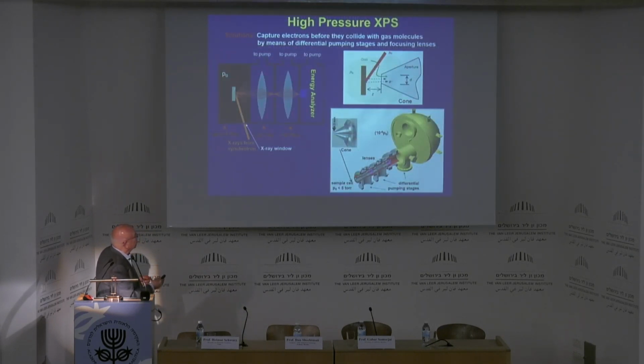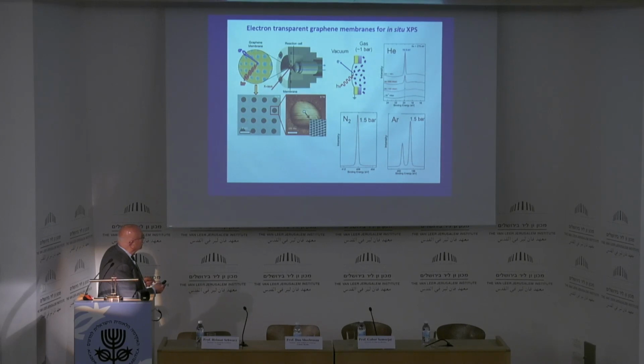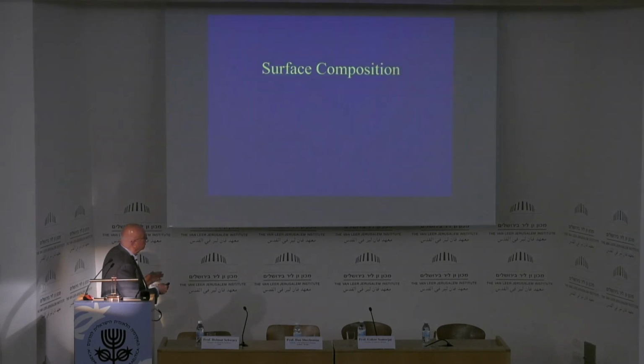Now, X-ray photoelectron spectroscopy can be used now at up to 10 torr, and it gives you composition analysis on the surface, and lately the graphene coating is very important to study what's on the surface, and it can show through liquids or high pressure gases which are existing on the other side of the graphene membrane.